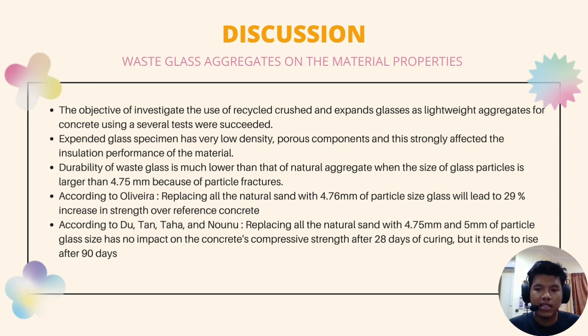We also find some weaknesses. For example, the expanded glass specimen has a low density, porous component, and this strongly affects the insulation performance of the material. The durability of waste glass is also much lower than the natural aggregate when the size of glass particle is larger than 4.75 mm because of particle fracture. But according to Oliveira, replacing all the natural sand with 4.75 mm particle size glass will lead to a 29% increase in strength over reference concrete.